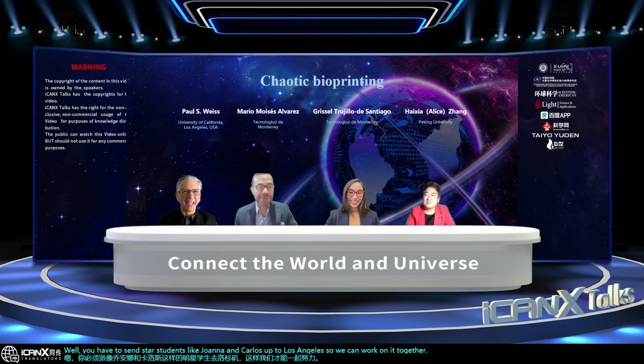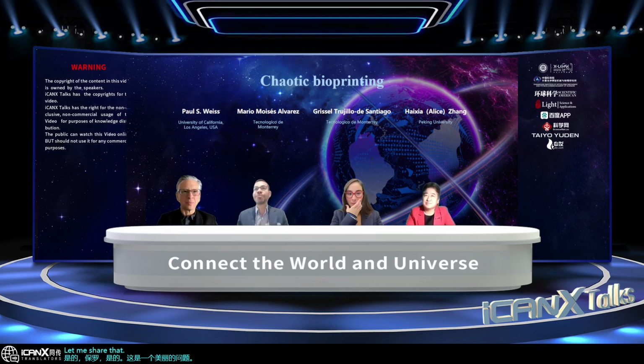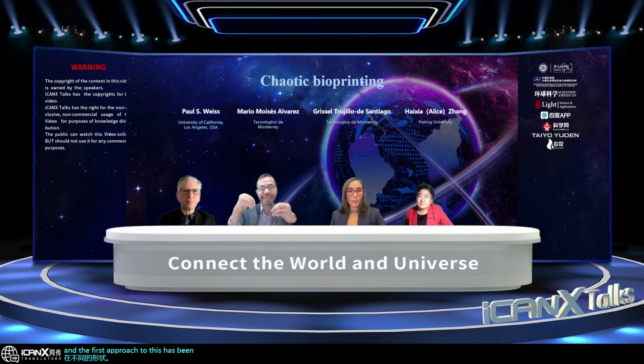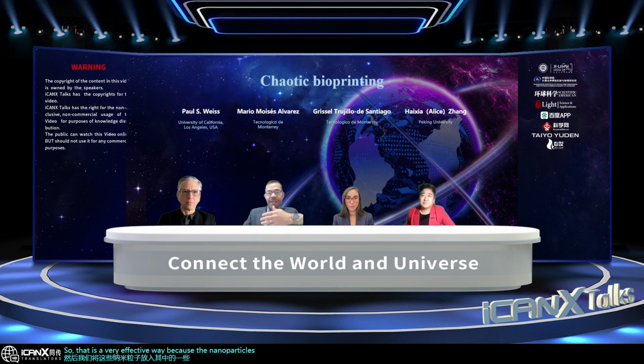Yes, Paul, yes. That's a beautiful question. Let me share one idea on which we are starting to work, which is functionalization with different enzymes in different channels. The first approach to this has been immobilizing enzymes in nanoparticles, and then we feed these nanoparticles in some of the streams. That is a very effective way because the nanoparticles will not diffuse through the hydrogels once they are cross-linked. So the mobility of these nanoparticles is basically negligible. So you have functional layers now.